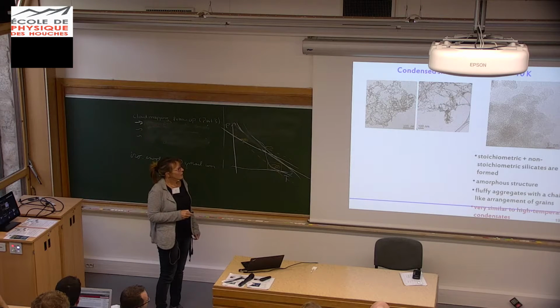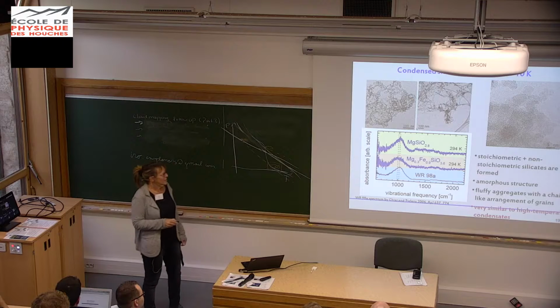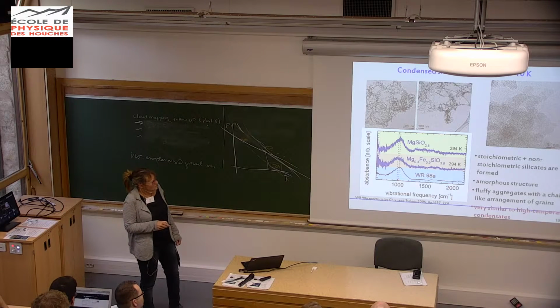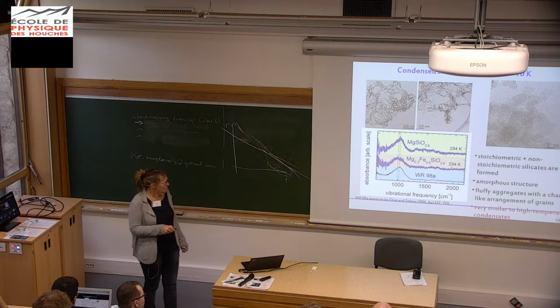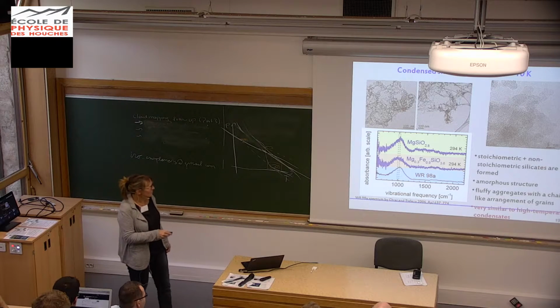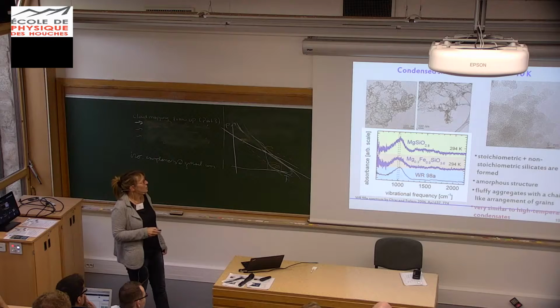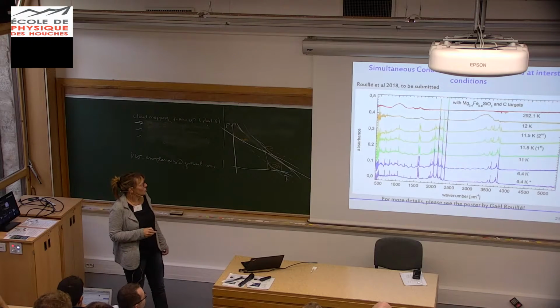This is a comparison to the interstellar silicate emission band, measured by Chiar & Tielens 2006, and you can see it's a very nice agreement with this interstellar emission band. This is not so important.